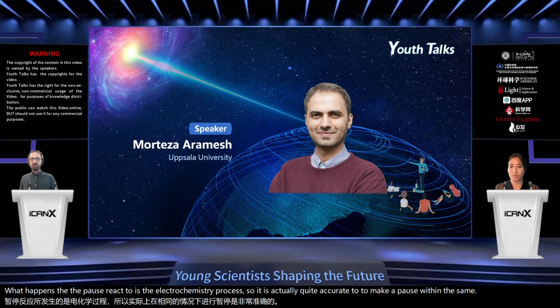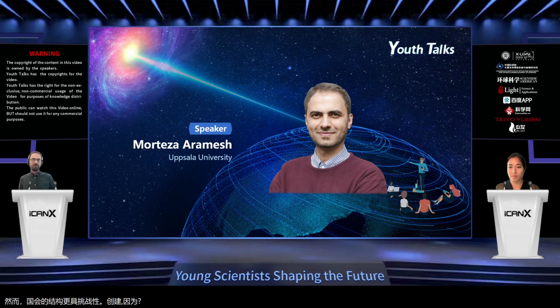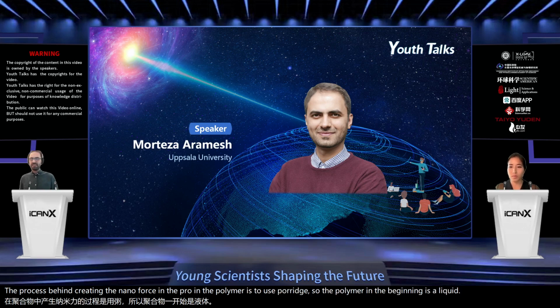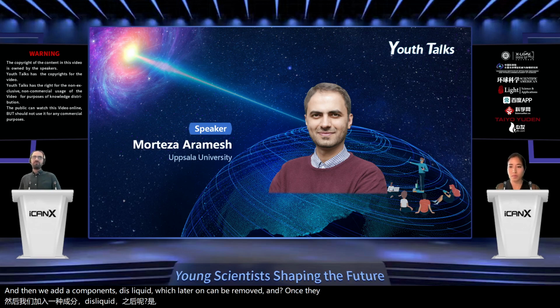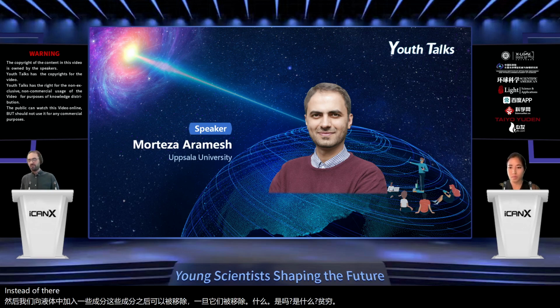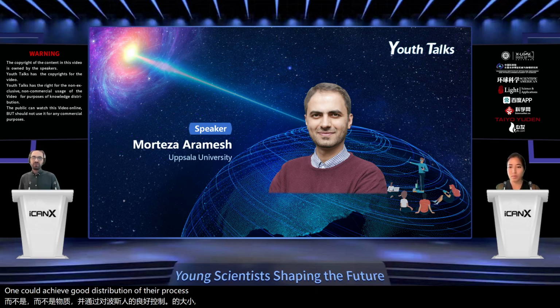It was, however, a bit more challenging with the polymer structures that we're creating, because the process behind creating the nanopores in the polymer is to use porogen. So the polymer in the beginning is a liquid, and then we add components to this liquid, which later on can be removed. And once they are removed, what remains is a pore instead of the material. And by having a good control over the porogen size, one could achieve a good distribution of the pore sizes in the polymer structures too. So now we can achieve a range that is satisfactory for our application, for example.